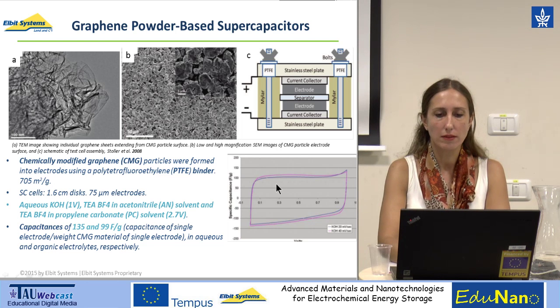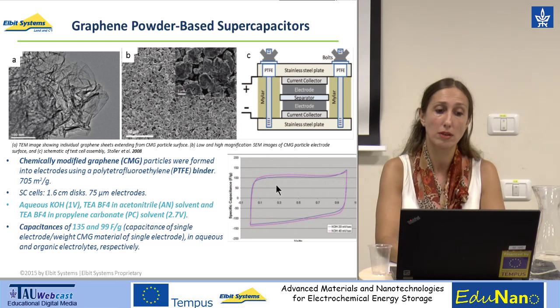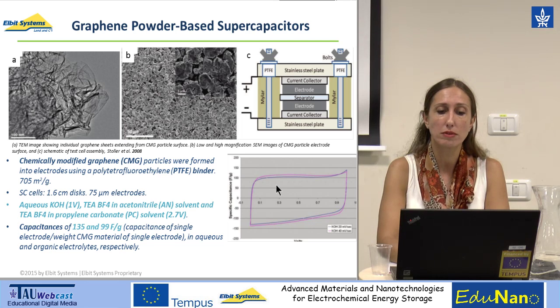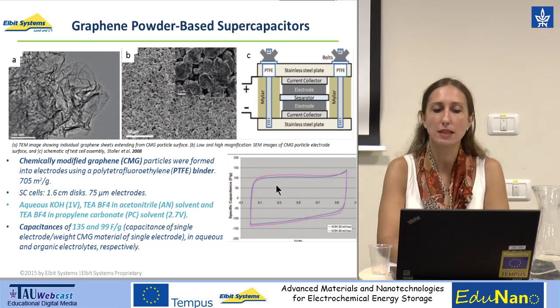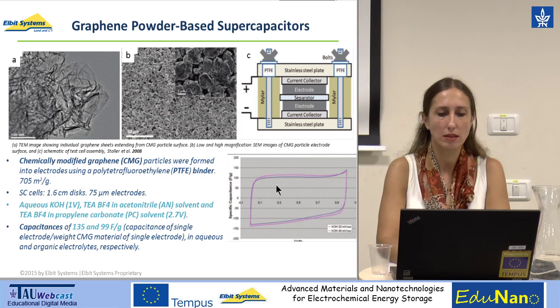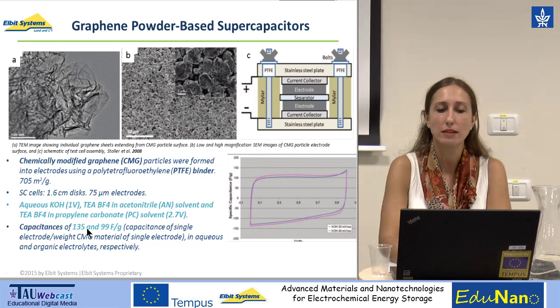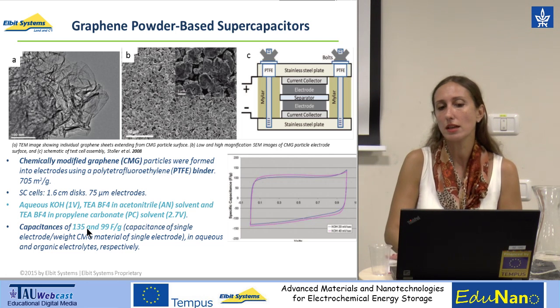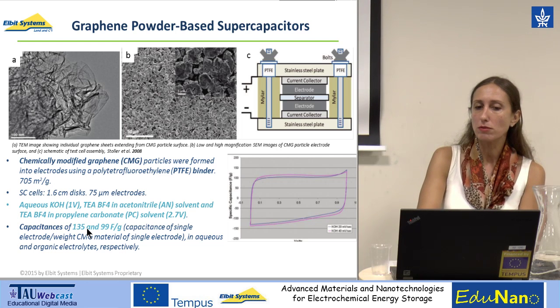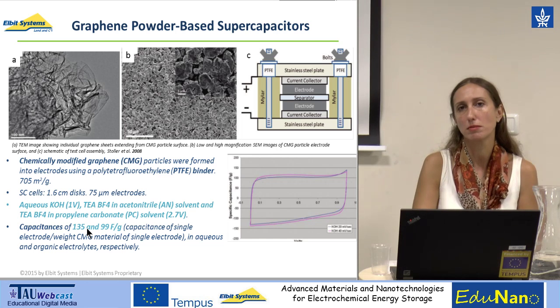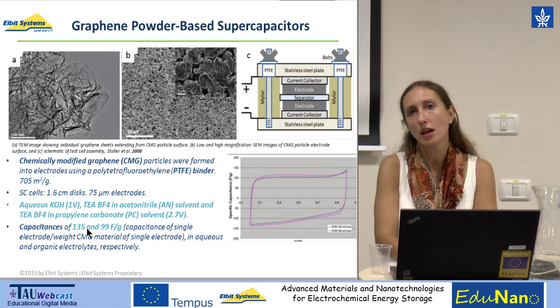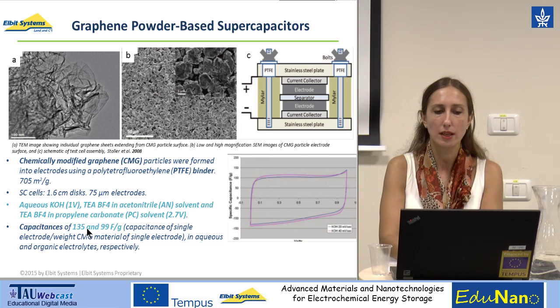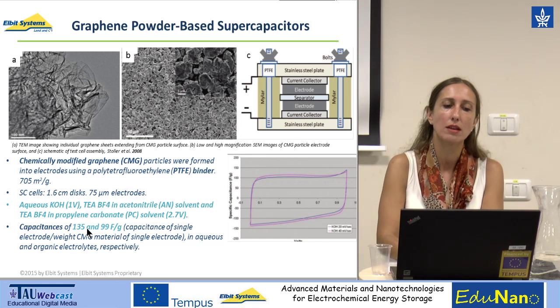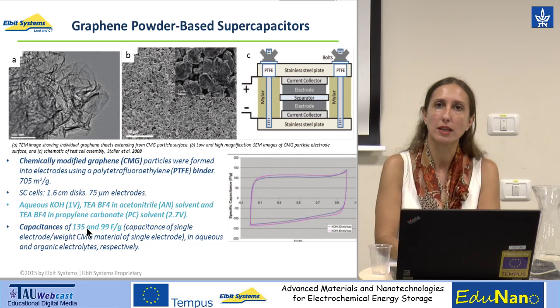The capacitance value for this aqueous-based chemically modified graphene supercapacitor was 135 farad per gram. This is the capacitance of a single electrode per weight of CMG material of the single electrode, whereas for an organic electrolyte it was 99 farad per gram. So it's completely a substitute of activated carbon. For aqueous media or aqueous-based supercapacitors, these kind of values of 135 farad per gram, these are very known values, even when you use activated carbons, but not activated carbons at the 700 square meter per gram area, then you have a lower specific capacitance, by let's say 20 or 25 to 30%.